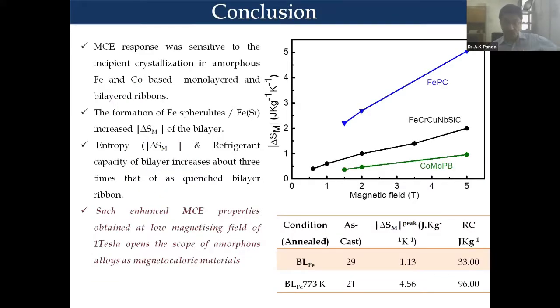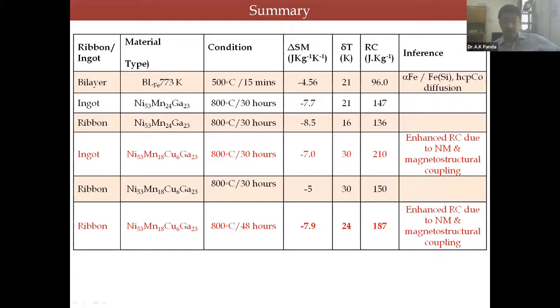I just try to go for a couple of slides. This is just to compare our work: with bilayered amorphous ribbons, you can get much more promising entropy compared to any of the single layered amorphous ribbons. So this is how we can get it. With bilayered ribbons, you can get an entropy of say 4.56 joules per kg per Kelvin and a fairly good refrigerant capacity of 96 joules per kg. So this is just a comparison to tell you that, nevertheless, nickel manganese gallium shows high entropy and refrigerant capacity. Even bilayer ribbons show 4.56, but please keep in mind that we can apply very low magnetizing fields to get the entropy, and therefore the amorphous materials may be emerging in future as magnetocaloric materials.